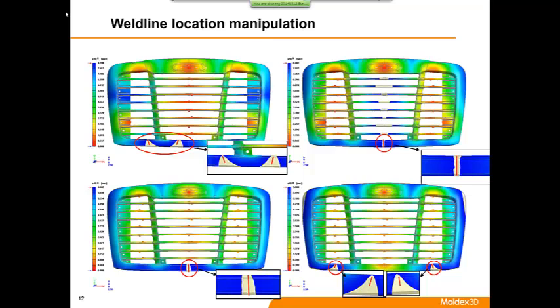This is another example showing that using different gates we can test on the gate design. So this is a front grille, and you can see from these 4 different designs we can have a lot of different combinations of the weld lines. And not only on the location, we can also estimate the weld line temperature. So location, of course, we want it to be in a less visible place, but if the weld line temperature is too low, it's still doing a lot of damage to the structure. But if we can also raise that weld line temperature by making the 2 melt fronts hotter than before, we still have a very strong joint in between and make them less visible.